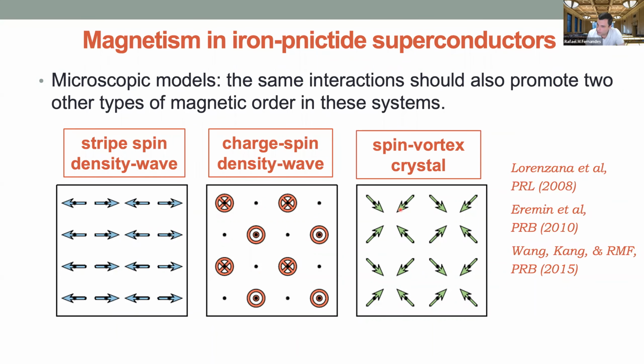Now, you can take a step back and ask, if I write down a model for these two order parameters, eta 1 and eta 2, is the striped spin density wave the only game in town? And the answer is no. There are two possible other phases that can appear. One is what's called a charged spin density wave, where both eta 1 and eta 2 are non-zero and parallel, or what we call the spin vortex crystal, where both eta 1 and eta 2 are non-zero, but they're perpendicular.